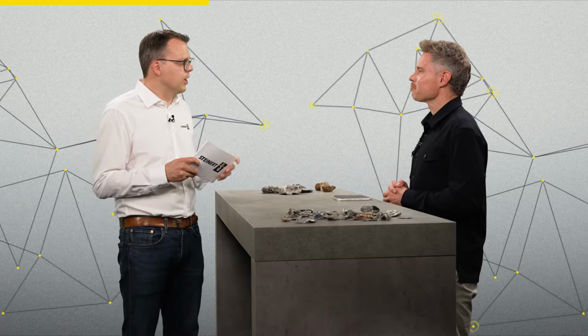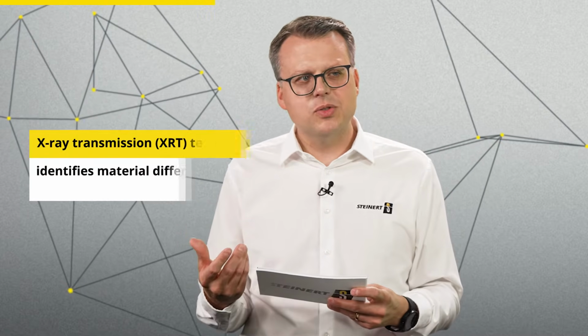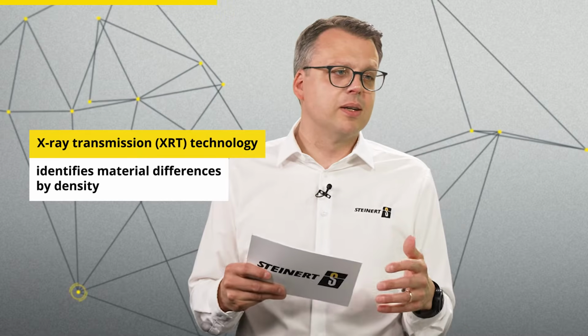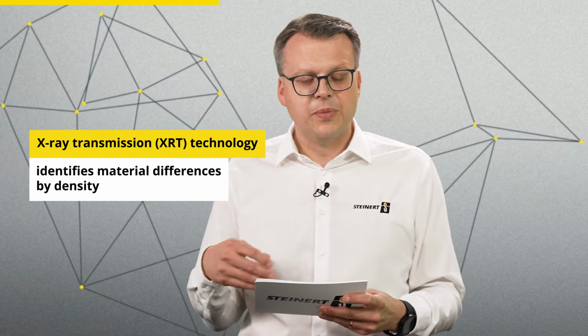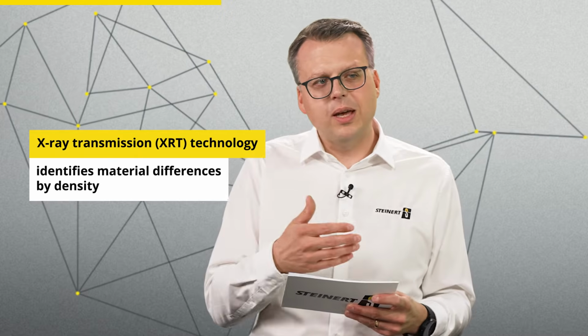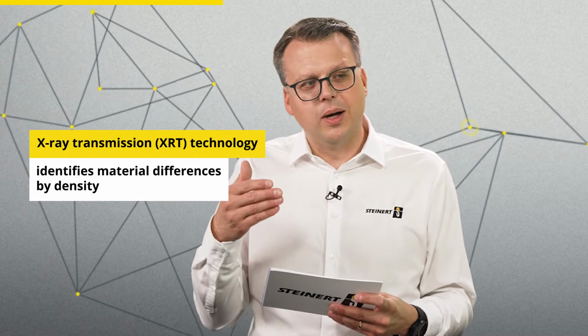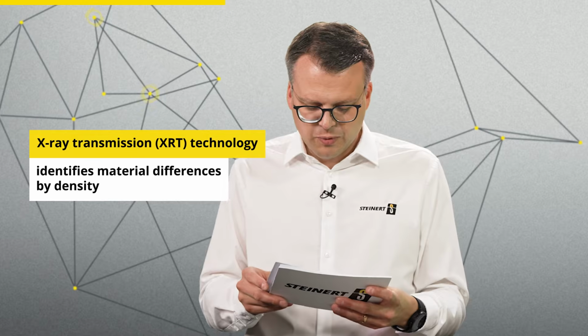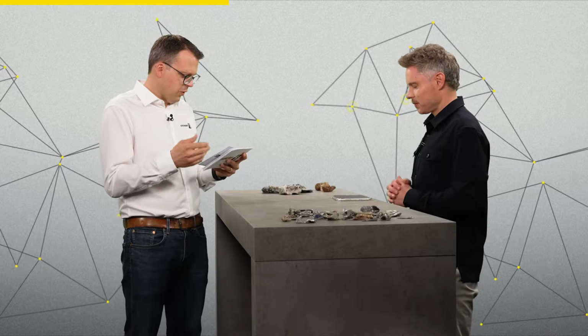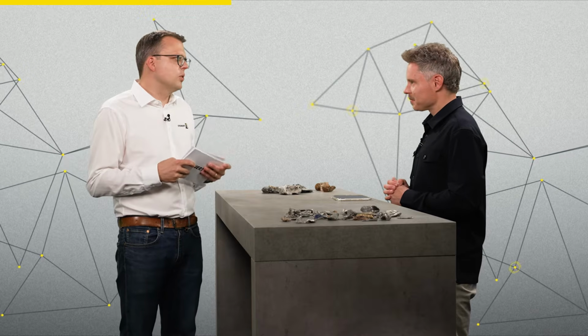a real benchmark here. And these eddy current separators are typically followed by X-ray transmission sorters to do a dry density separation step. Here we typically separate free heavy metals, but also heavy metal compounds from the aluminium, so from the light fraction. And then, of course, we also can go deeper into sorting by segregating the aluminium into cast and wrought, for example, and even into different alloys.